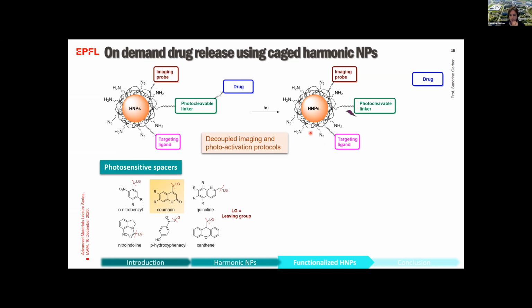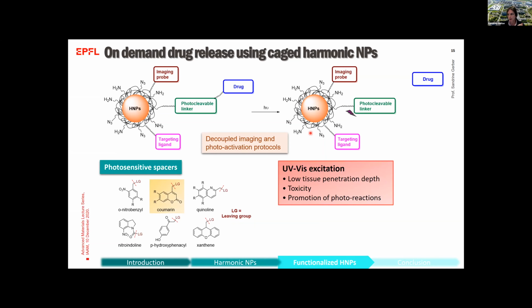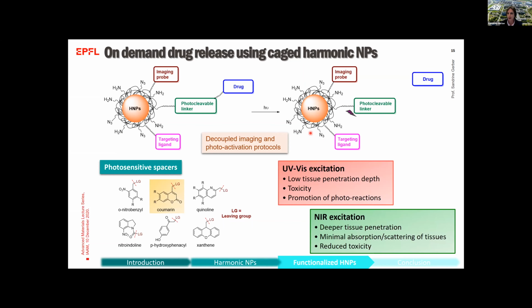Most of the photosensitive spacers are activated by UV-visible excitation, and we know that this UV-visible excitation has low tissue penetration depth, can be toxic for cells and tissues, and also promotes photoreactions. So there is a high advantage to use near-infrared excitation, which has deeper tissue penetration, minimal absorption and scattering in this window, and reduced toxicity.